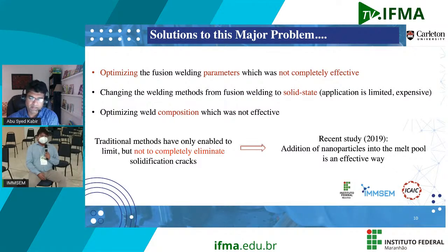So there is a recent study published in Nature Materials, I believe, a couple of years ago. They proposed a solution that if you add nanoparticles in the melt pool, in the 7075 melt pool, you can actually eliminate the solidification crack completely.